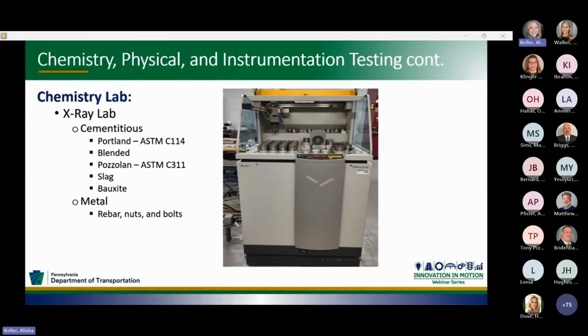These samples are mixed with a powdered flux that acts as a diluent and burned over 1,000 degrees Celsius to form a glass disc. The disc is then X-rayed to determine the percentage concentration of oxides within the cement. We look at how much calcium oxide, silica oxide, and other oxides are within the material. We evaluate it to make sure that it meets the specification listed in the report sent to us by the company.